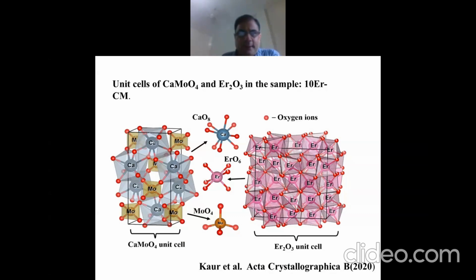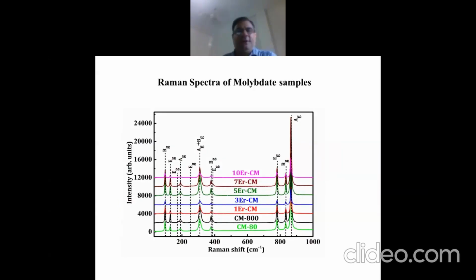And we did the Raman measurements of calcium molybdate as well as the tungstate samples. This is the Raman spectra of calcium molybdate samples doped with erbium oxide, and we see several sharp peaks because of the crystalline nature of the samples. For the sample which is annealed at 80 degrees Celsius, the peaks are broader. But as you increase the annealing temperature to about 800 degrees Celsius, the peaks sharpen.